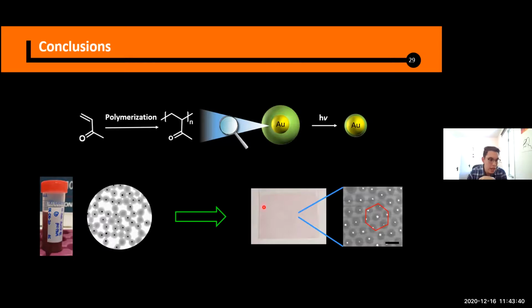For that, I have been using, I didn't show anything about the technique, but I'm coating a microscope slide, the typical one, by dip coating this substrate in the solution containing these particles, and by controlling the speed of the dip coating and also the surface pressure of the particles that are at the interface of water and air, we can easily deposit these particles on the surface. And what is interesting is that these particles can be arranged in a hexagonal way. And this type of structure has other very interesting optical properties that we're going to start exploiting in the next months.